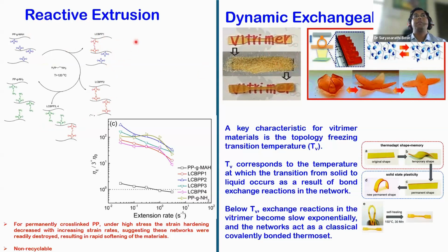So in the case of reactive extrusion, you might be able to get upcycled properties, but that's only once. When you try to recycle them, you will again face the problems. And there are studies which show how strain hardening decreases with increased shear rates or strain rates in the case of reactive extrusion, where the bonds are permanent. Whereas if you introduce dynamic bonds, then you should be able to make very useful products post its useful life, because you have a topology freezing temperature which allows it to recycle at a particular temperature.